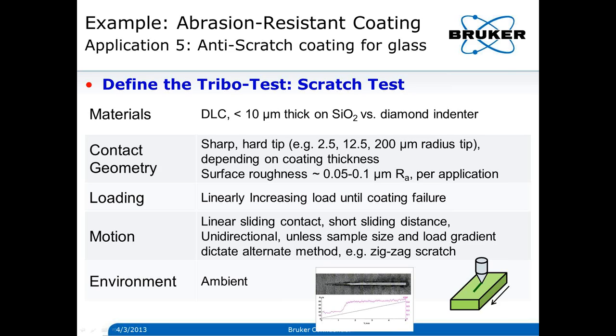This is a very common and effective test to simulate what a piece of sand would do to your touch screen coating. The scratch test with linearly increasing load works well for simulating this real-life situation. At some point the coefficient of friction plot shows a step function — we've broken through the film and are seeing what's below it. This is a very nice test to see at what load we've caused film failure, and is a very common test to run in the lab for abrasion-resistant coatings on glass.